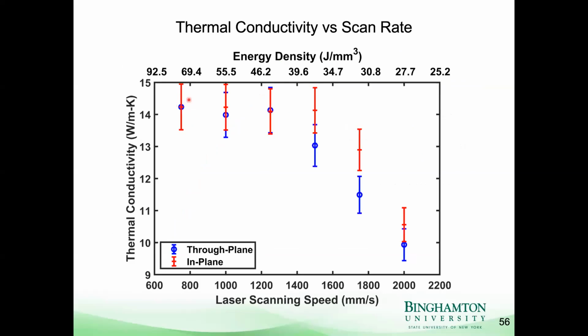So this is a plot of thermal conductivity versus laser scan speed. And at too high a scan speed, so at 2000 millimeters per second, you might remember we had some porosity. And so it's natural that the thermal conductivity of that is lower. At slower scan rates near where there's very low porosity, the thermal conductivity was kind of plateaued here, just like the porosity was. And then kind of in between that, we see that the through plane conductivity here in blue decreased and was lower than the in plane conductivity.